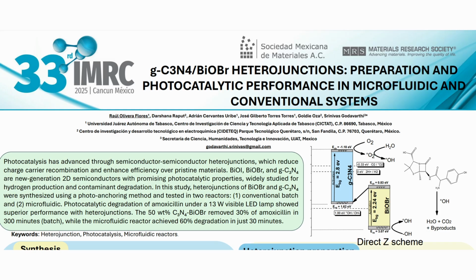The microfluidic system shows superior performance in degradation of amoxicillin using these heterojunctions, reaching 60% of degradation in only 30 minutes. Otherwise, the batch reactors achieve 30% of degradation in 5 hours.